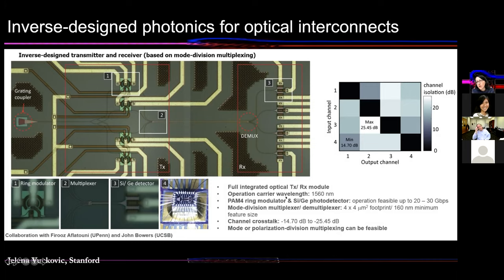And we've recently collaborated with John Bowers and Alan Willner on measurement of bit error rates and also high-speed operation in this system. And we're very excited about the results. But the measurements that you see here are low-speed measurements we did at Stanford. And we have excellent channel crosstalk measured, and excellent, minimized input loss into the system. So this is already getting into the level of much more complex optoelectronic and integrated photonic circuits relative to our initial work with simple elements done in a foundry.